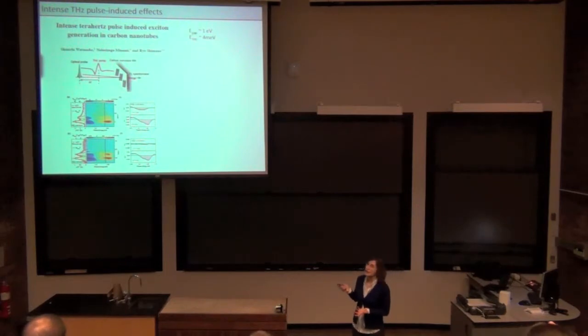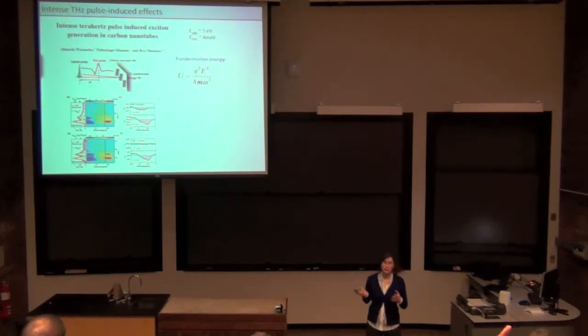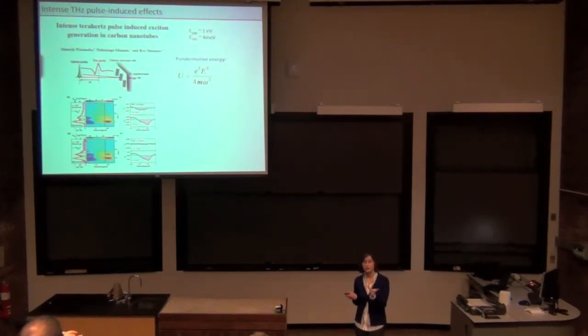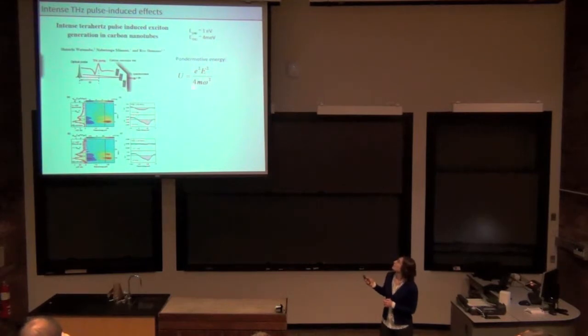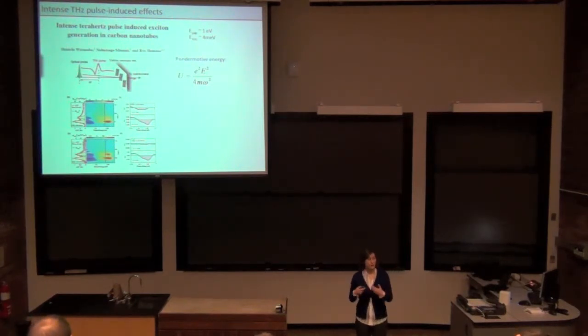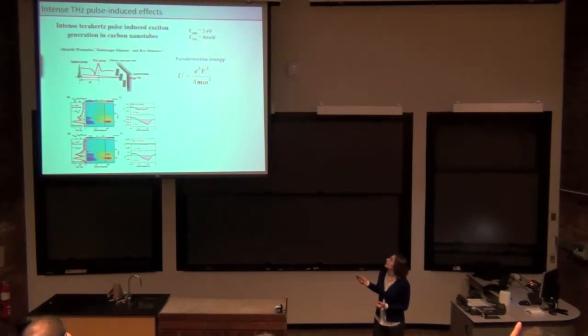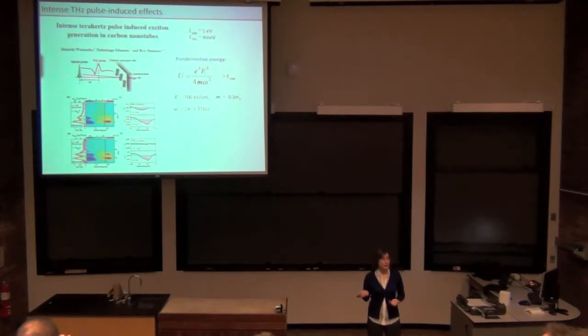3 orders of magnitude higher than the energy of a single terahertz photon. What they believe is happening is that you need to consider what's called ponderomotive energy, which is the cycle average energy of electrons oscillating in an AC electric field. It depends on the electric field, but also inversely on the square of the frequency. The frequency of terahertz radiation, of course, is much lower than optical radiation. And in carbon nanotubes, the mass is also quite low, so this energy becomes much larger than the band gap. So what they believe they're seeing is some sort of tunnel ionization. They're ionizing across the gap, and that's how they're creating the excitons.